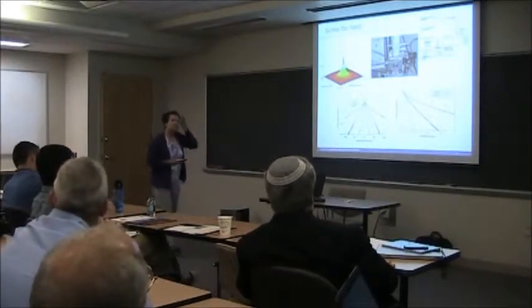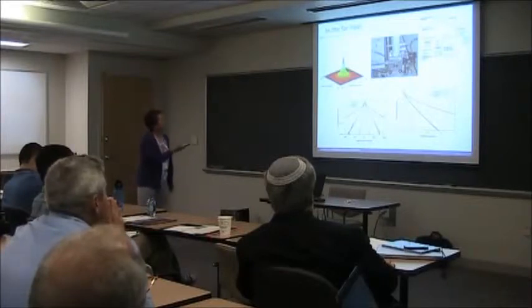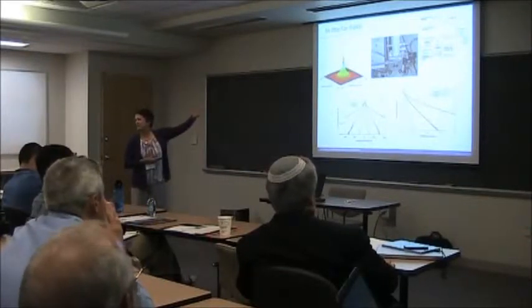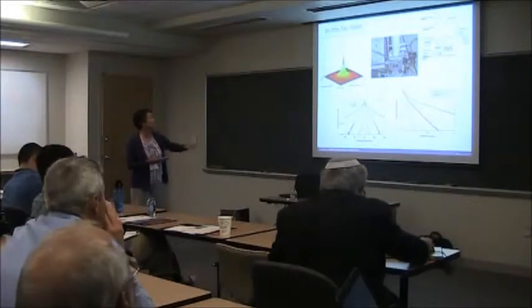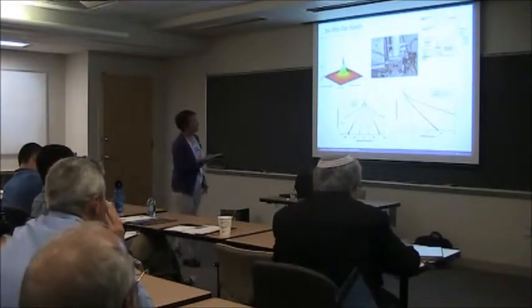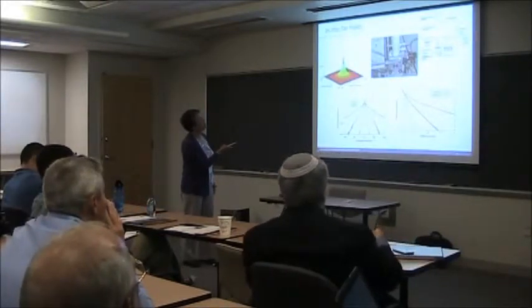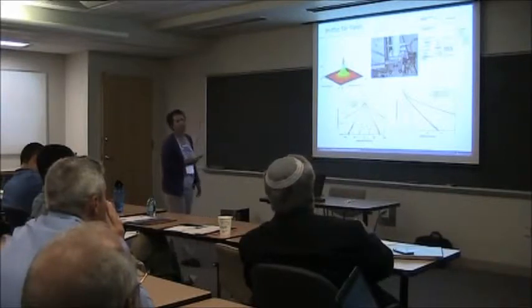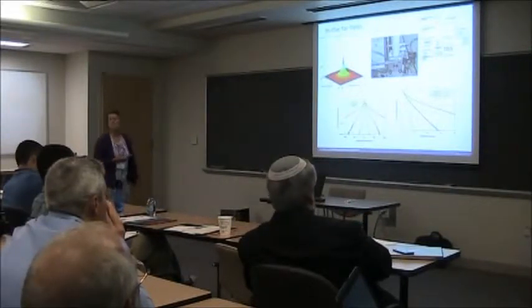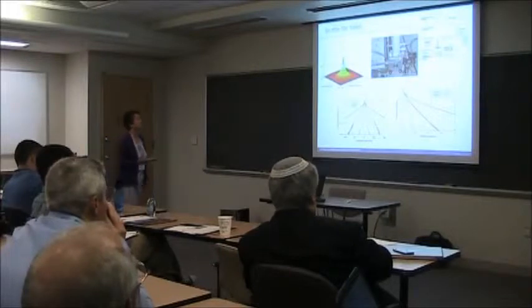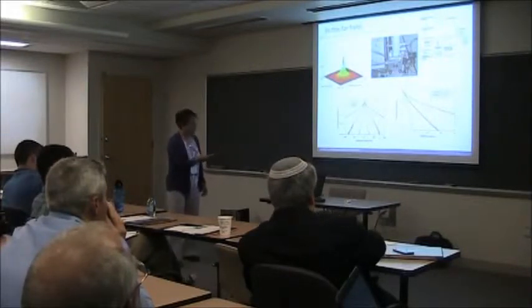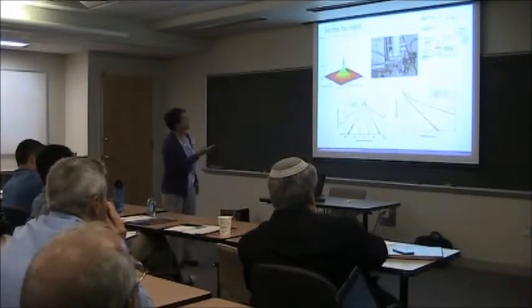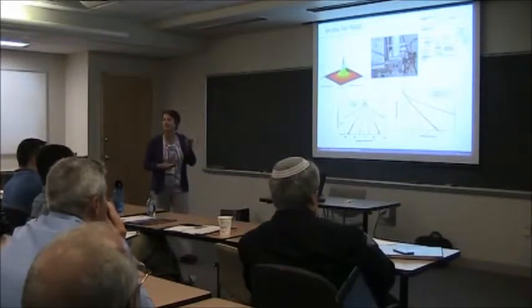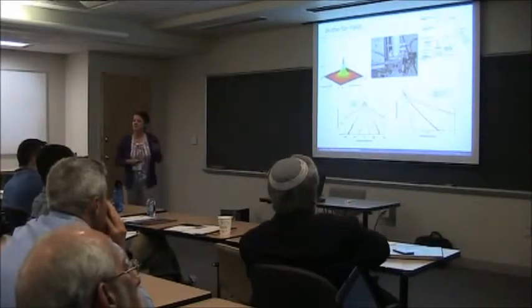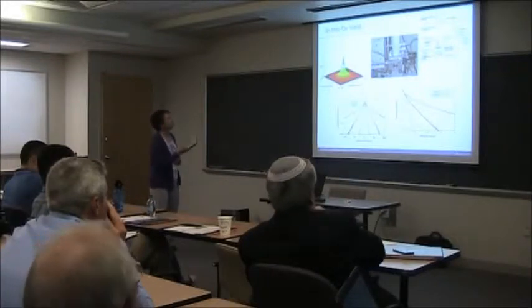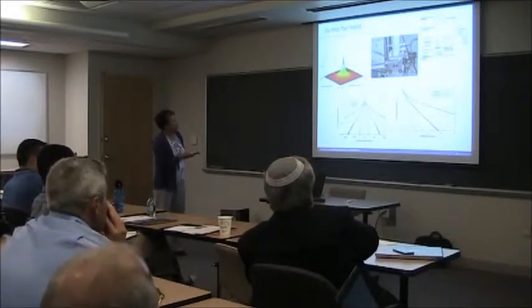So we've been doing this in the far field for a while. And again, here's an image, and this is not a simulation. This is actually spatially resolved luminescence. And we did this initially just by putting a CCD camera and an optical microscope into a very old but very functional JEOL 840 SEM. I won't go through all the details because I want to focus on the near field work. But basically, you collect pictures like this, which tell you a lot about the mobility lifetime product of your material and carrier transport. And then you can fit the data.